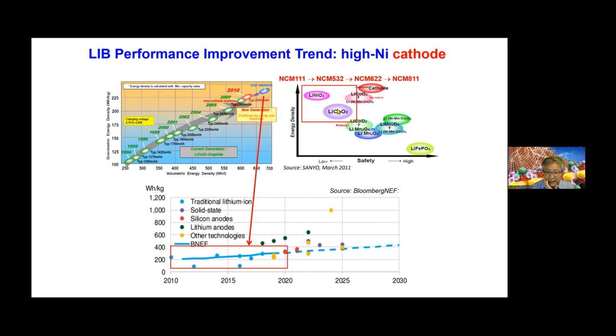Starting from lithium cobalt oxide, and over the last 30 years or so, there's been extensive development of energy density, gravimetric, the energy density in watt hour per kilogram, or volumetric density, because we are densifying the material. It has been increasing, and right now it's about 300 watt hour per kilogram. That's the current status, and certainly, depending on the choice of different electrode material, especially on the anode side, lithium metal or other types of anode material, silicon anode, can change the energy density. Those are technologies under development.